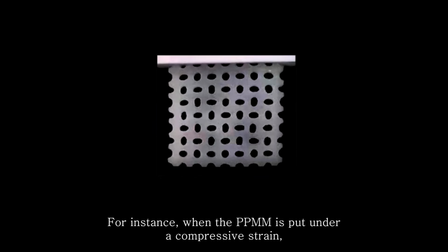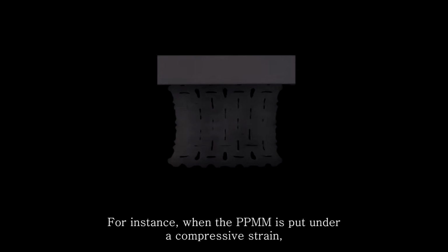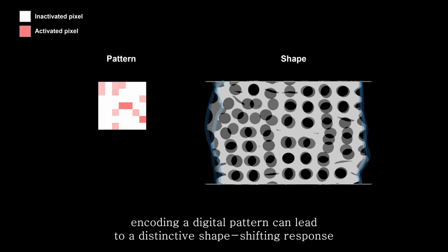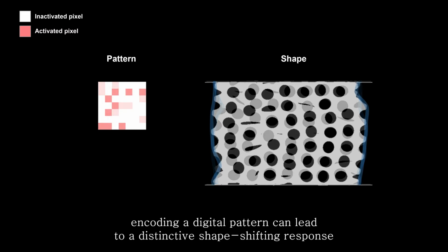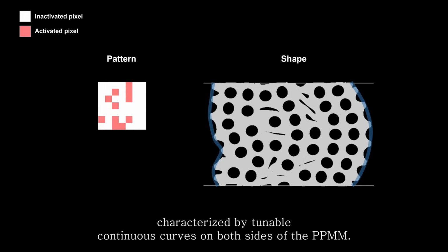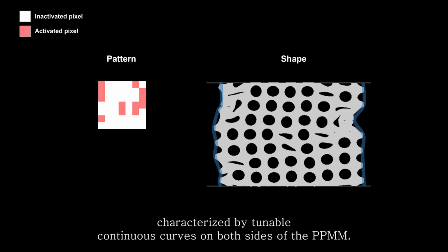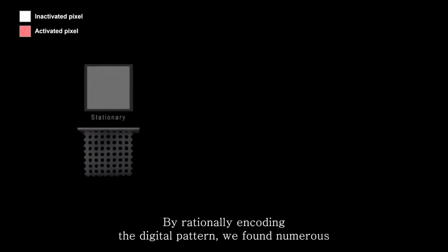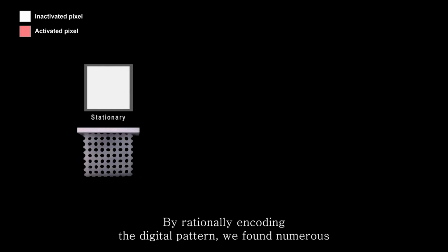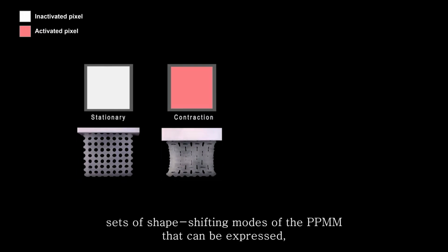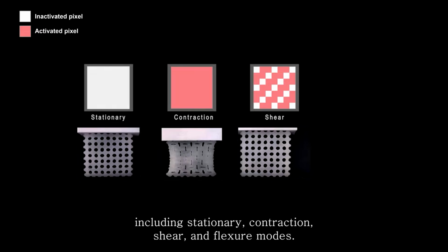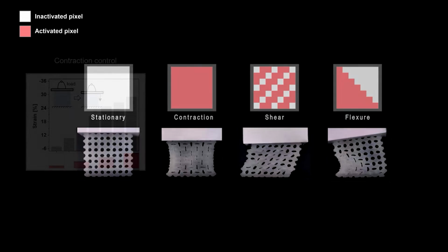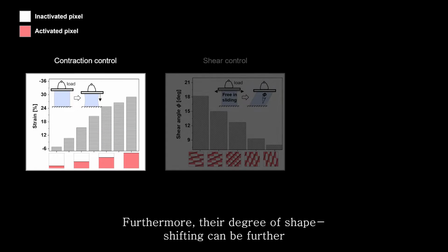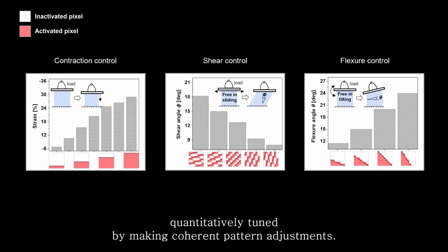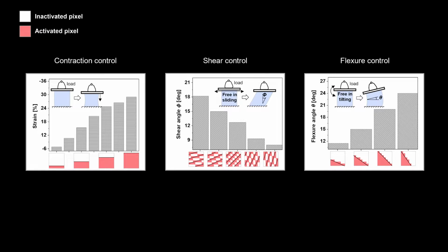For instance, when the PPMM is put under compressive strain, encoding a digital pattern can lead to a distinctive shape-shifting response characterized by tunable continuous curves on both sides of the PPMM. By rationally encoding the digital pattern, we found numerous sets of shape-shifting modes of the PPMM that can be expressed, including stationary, contraction, shear, and flexure modes. Furthermore, their degree of shape-shifting can be further quantitatively tuned by making coherent pattern adjustments.